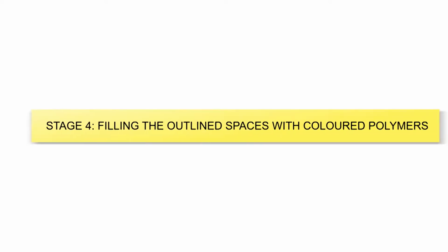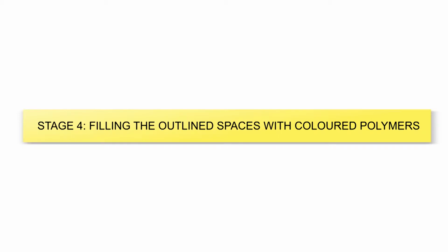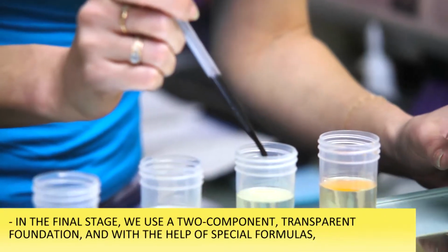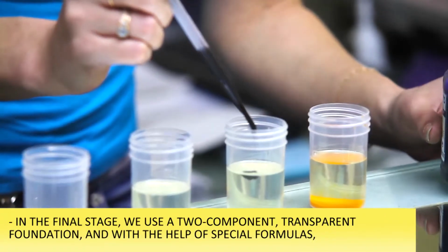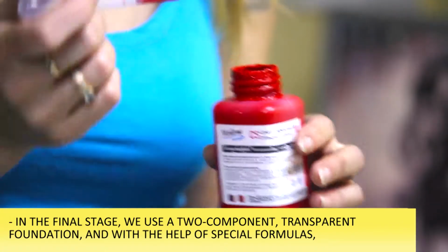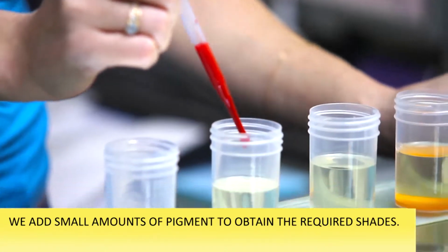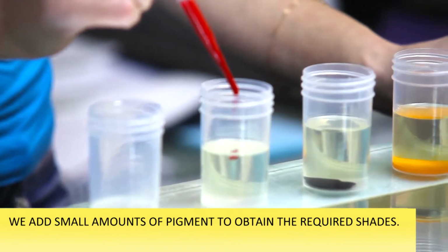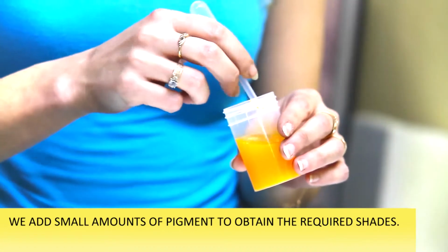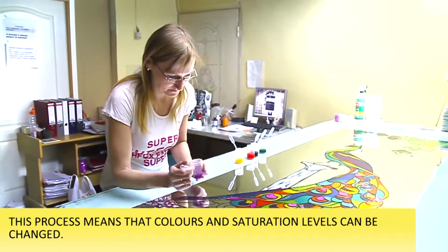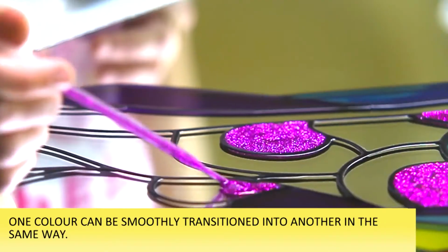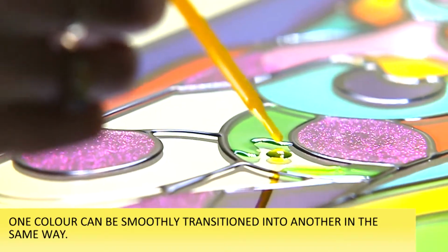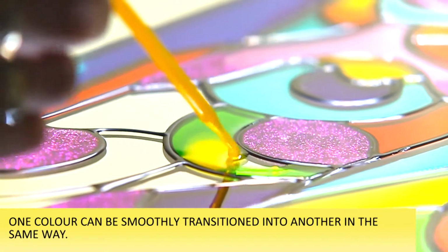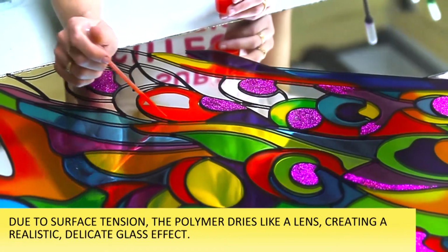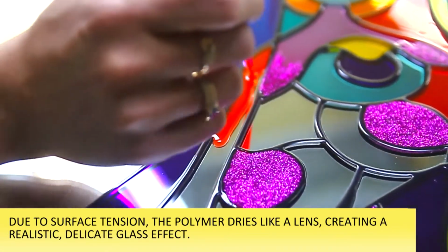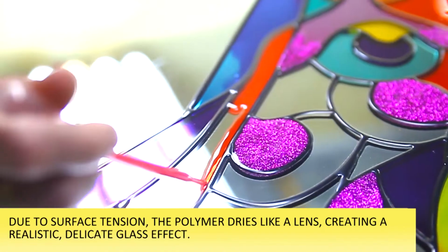Stage 4. Filling the outlined spaces with colored polymers. In the final stage, we use a two-component transparent foundation, and with the help of special formulas, we add small amounts of pigment to obtain the required shades. This process means that the colors and saturation levels can be changed. One color can be smoothly transitioned into another in the same way. Due to the surface tension, the polymer dries like a lens, creating a realistic, delicate glass effect.